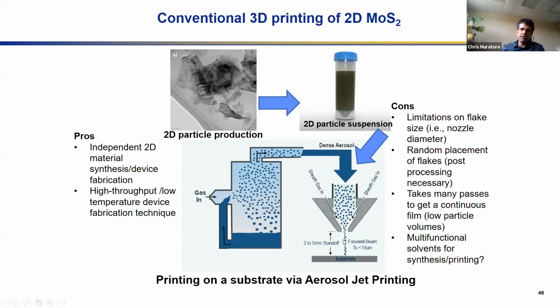And there's lots of different ways to print particles on surfaces. All of them have a lot of challenges, right? Because over time, you preferentially lose the solvent, so your concentration of the particles increases with time. You will inevitably, as the solvent evaporates, change the viscosity of the solution, and you'll inevitably clog the printing head. There's a lot of challenges associated with printing, but it's still a pretty attractive technique because you can put this array of particles on the surface in the pattern that you want at room temperature.